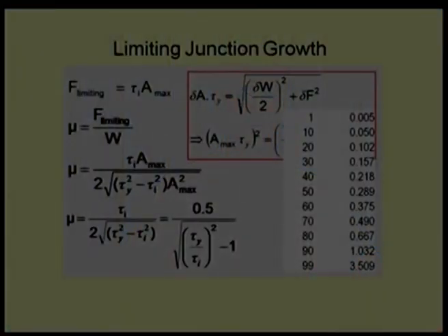Let us take an example where tau I by tau y is given in some ratio. Let us take tau I divided by tau y as 1%, or 0.01. In that case, if the interface shear strength is just 1% of the soft material shear strength, the coefficient of friction is almost negligible, 0.005.